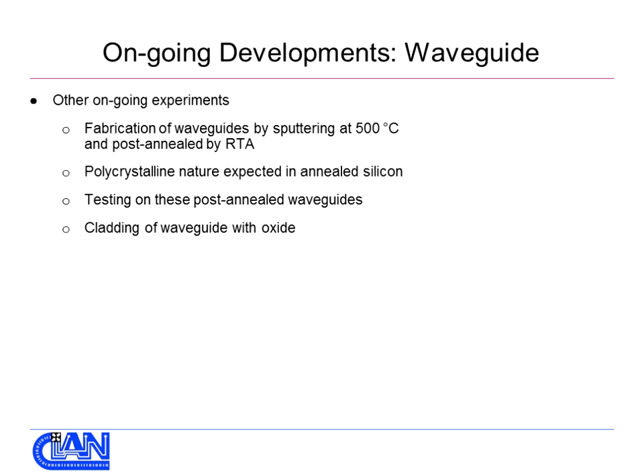So in the future, for the waveguide, what we really hope to get to is fabricating the waveguide by sputtering at 500 degrees and by post-annealing. So why do we want to add in these temperatures at these different times? Ultimately, we want to get a more polycrystalline structure to the silicon for our waveguide, because we believe in theory that it should be a more effective waveguide if it has heating in the process somewhere along, so it can change into a polycrystalline structure.